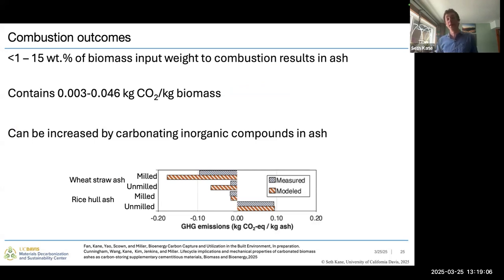So we're seeing a negligible amount, up to about 0.05 kilograms of CO2 per kilogram of biomass. You, however, can increase that slightly by carbonating the inorganic compounds present. So for example, calcium oxide to calcium carbonate and store a little bit more CO2 in that material. And so this example here is from a paper by a PhD student that recently graduated from the group, Patrick Cunningham, where he treated different biomass ashes with CO2.